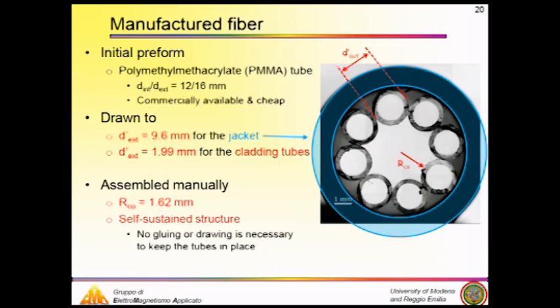So, this is a microscope picture of the circular tube lattice fiber that I've manufactured. I started from polymethyl methacrylate tubes, and these are the dimensions of the initial preform. PMMA is a commercially available polymer, and it's also very cheap, making the final fiber extremely cheap. These are the final dimensions for the jacket and the cladding tubes, giving a core size of 1.62 millimeters. Another important feature of this structure is that it's self-sustained, so no gluing or further drawing steps were required to keep the tubes in place.